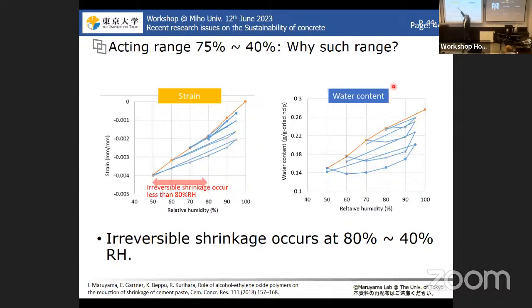And then if we put in the dehumidifying process, after returning to the different RH points, we found that from less than 80% to 40% or 50%, we see the irreversible shrinkage. But at the 80%, it is almost reversible here. So less than 80%, we see the irreversible shrinkage, something like this. So it seems that the SRA is acting on the shrinkage mechanism which produces the irreversible shrinkage.